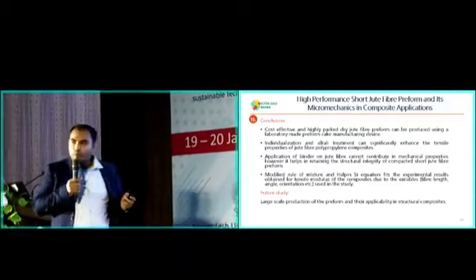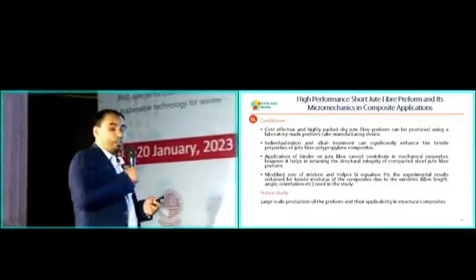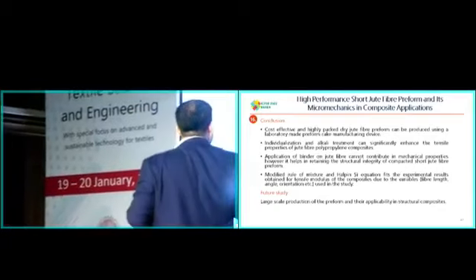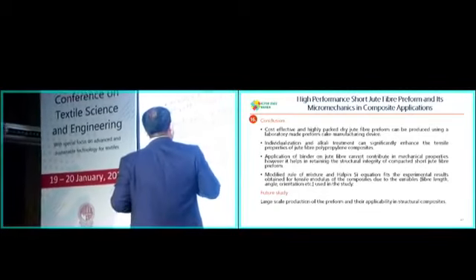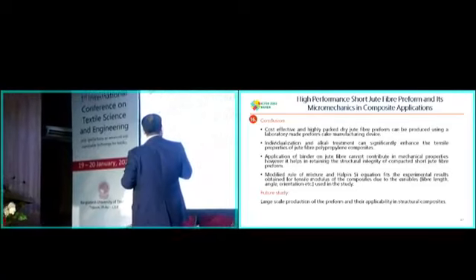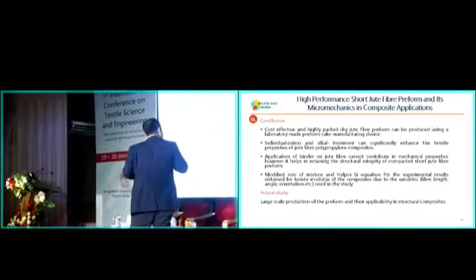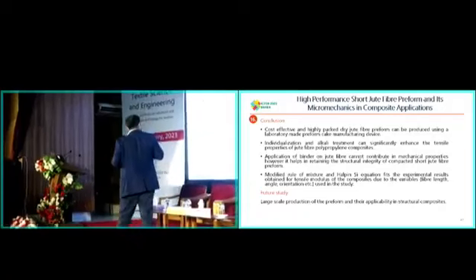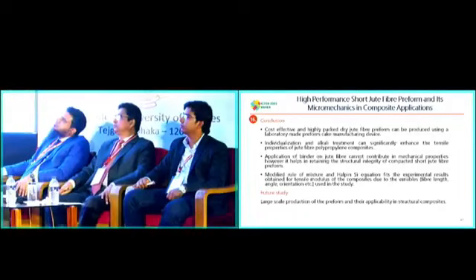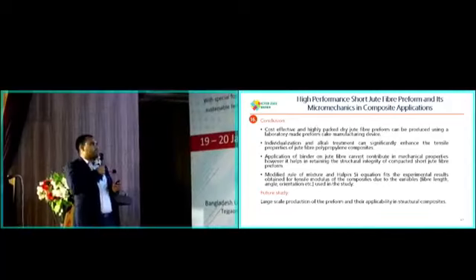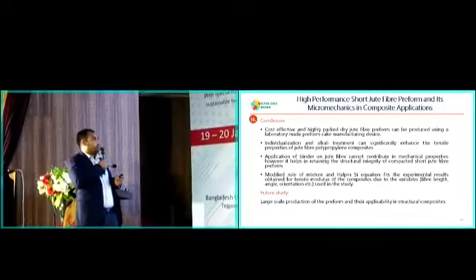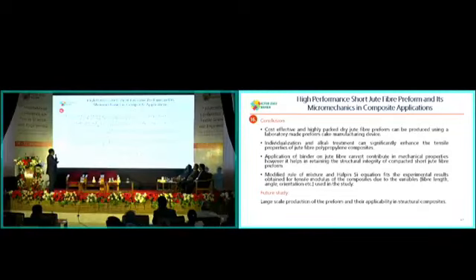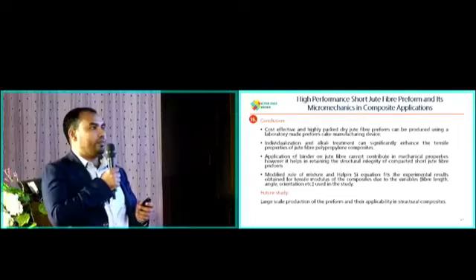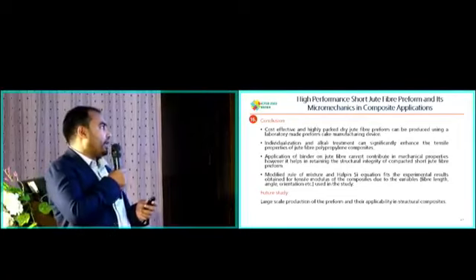So now we can conclude that yes, it is possible to produce a cost-effective and highly packed dry jute fiber preform using the laboratory-made preform cake manufacturing device. Individualization and alkali treatment can significantly enhance the tensile properties of jute fiber polypropylene composites. Application of binder on jute fiber does not contribute to mechanical properties. However, it helps in retaining the structural integrity of the preform. And the modified rule of mixture and Halpin-Tsai equation fit the experimental results obtained for tensile modulus of the composite, considering variables like fiber length, angle, orientation factor, etc.